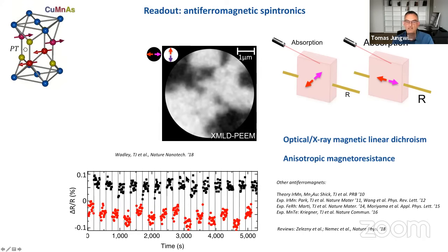What I'd like to emphasize here, and this is generic to the resistivity signals that we can detect in thin films, is that they tend to be relatively weak. That was the reason why in ferromagnets, people switched eventually to these multilayer TMR or GMR effects. So again, antiferromagnets are no exception. We work with simple films, and the resistivity change due to AMR we see is of the order of a fraction or maximum of the order of a percent.